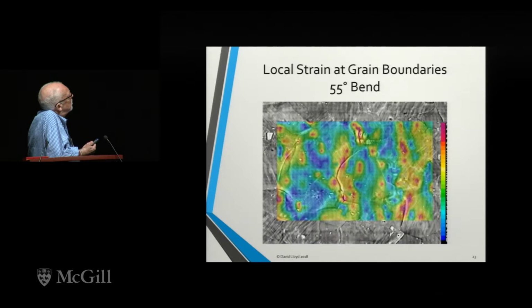And as you continue the bending, the local strains on the boundaries and within some of the grain features, the slip lines inside the grain, increase. But the strain also spreads along the boundaries. So as you continue bending, the number of boundaries showing the displacement increases, the strain locally associated with the boundaries increases, and it spreads significantly along the grain boundary.